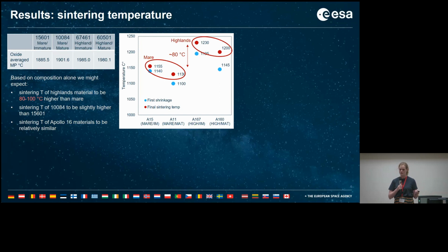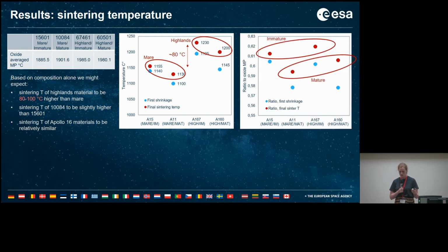So to examine this, we can compare the observed temperature to the oxide average temperature to look at the ratio. And here we see a really clear separation between the immature material and the mature material. We also see quite a difference in what I call the speed of sintering. So the point of sintering onset, and then the point between there and the point where it's well sintered.